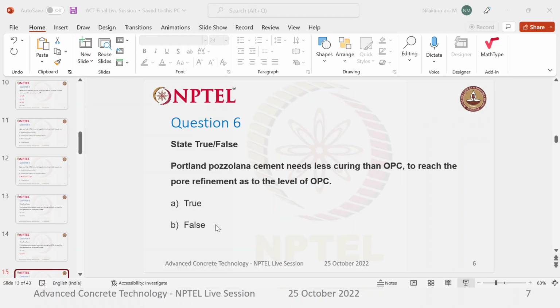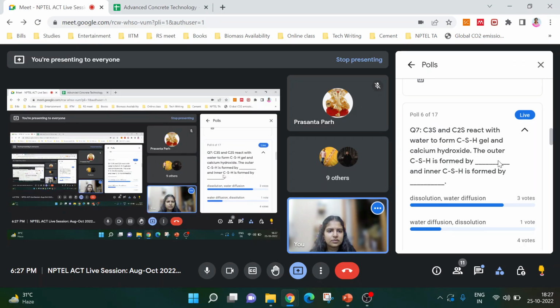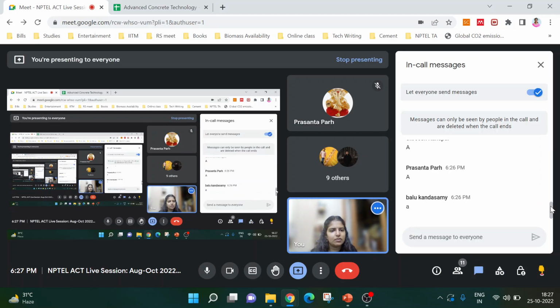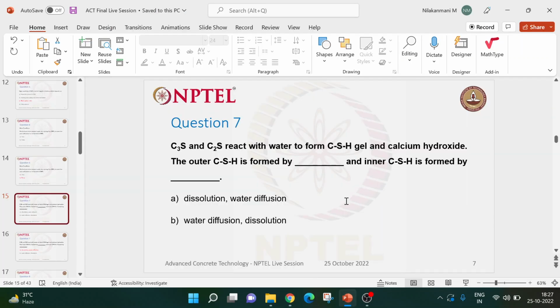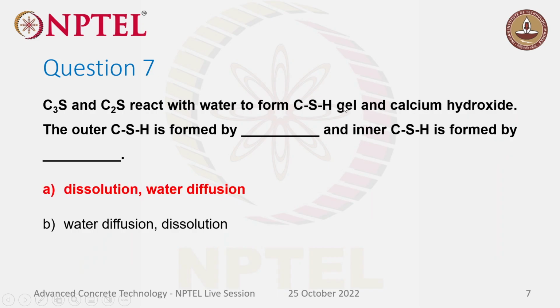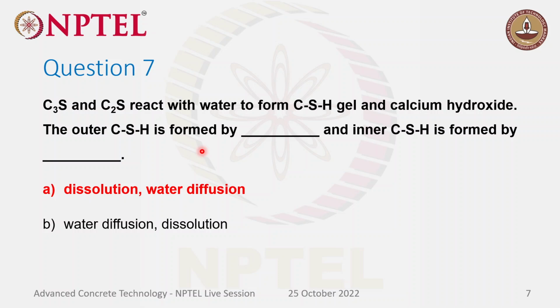Time is up. Let's see the class response. Most of you picked the right answer, because the right answer is option A. Outer CSH is formed on the outer region of the unhydrated cement grain. Initially the cement grains dissolve into the water, which then becomes pore solution because it contains ions now. So the outer CSH will be on the outside of the cement grain. It undergoes dissolution and forms the outer CSH.